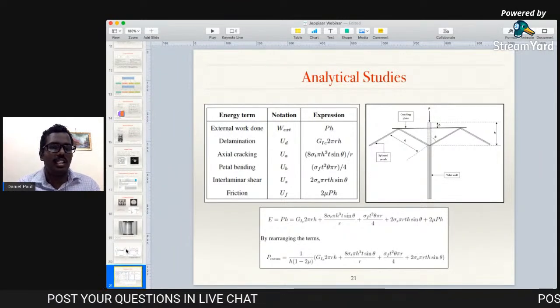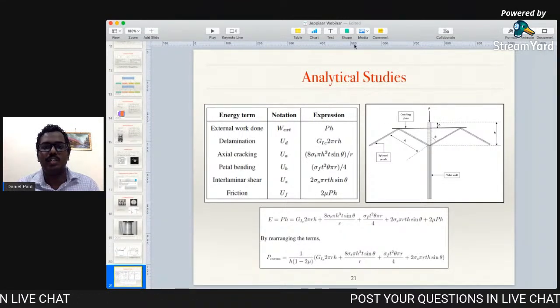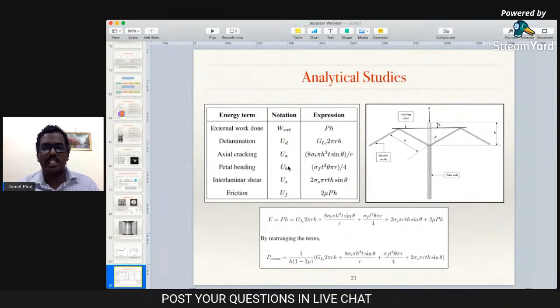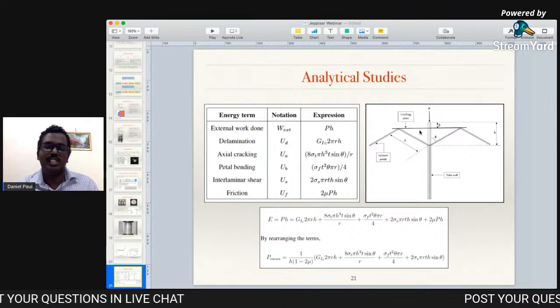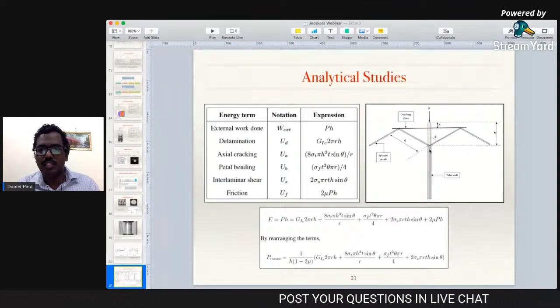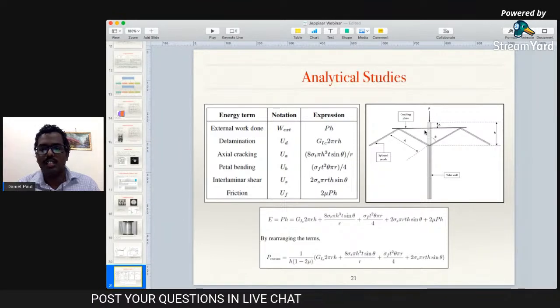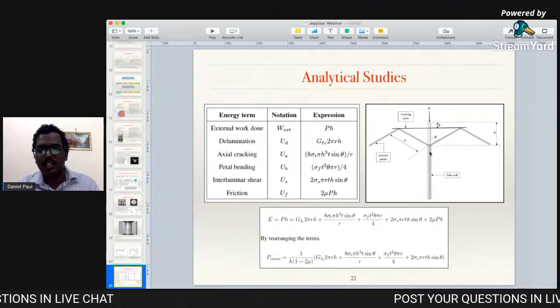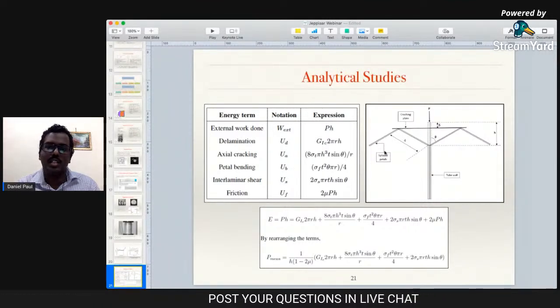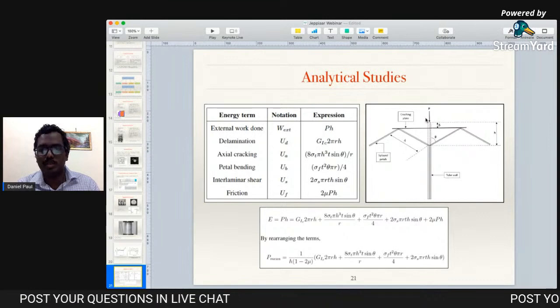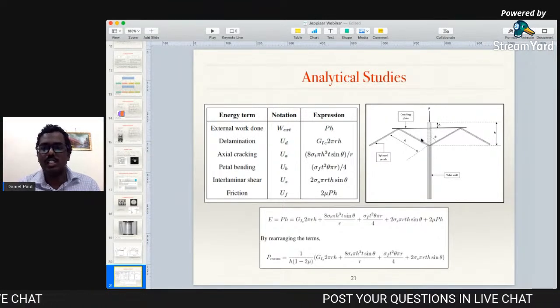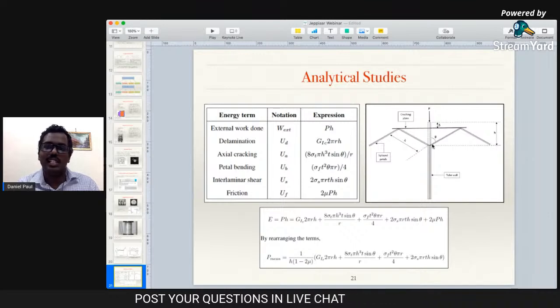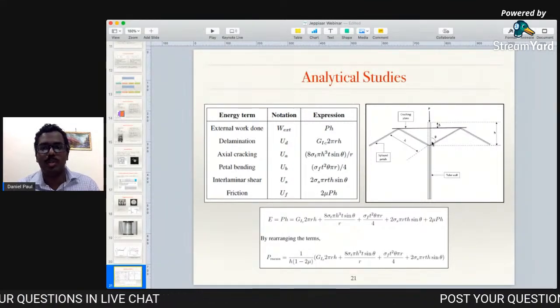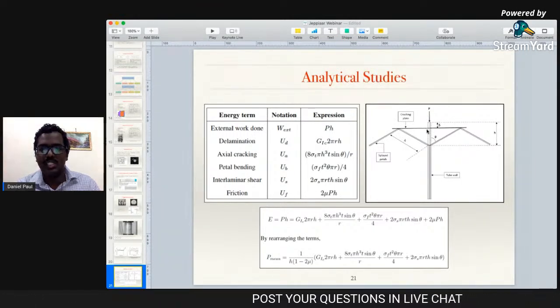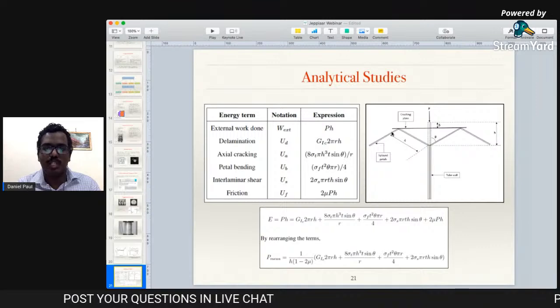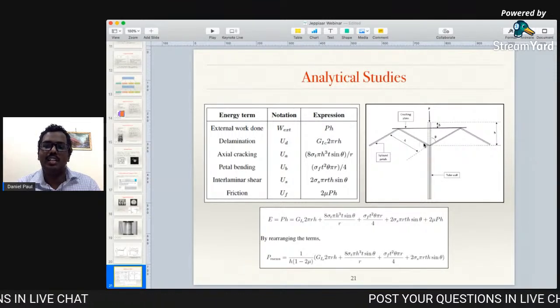And in addition to the experimental analysis, we also did a bit of analytical studies using an energy-based analytical model. In this also, what we did was quite simple. In the image, you can see that we have shown a cross section of a tube wall, which on compression is petaling in both directions, first splitting and bending in both directions. So we can analyze this as initially there is no splitting or bending, and when the crushing plate compresses the structure, it's going to split, bend, and create these petals,